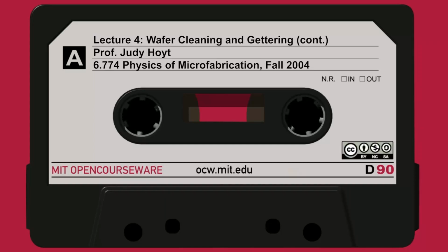And this expression in the middle of the slide, on slide 17, shows the diffusivity as a function of temperature. Gives you a rough idea. And the nice thing is you don't have to remove all the oxygen. You just have to get the level below a certain level. For instance, you need to get it from about 20 parts per million down to less than 10. If it gets low enough, the precipitation won't take place because, again, it'll be below the solubility limit, so you don't have to worry about precipitation. So you're just trying to reduce it down.